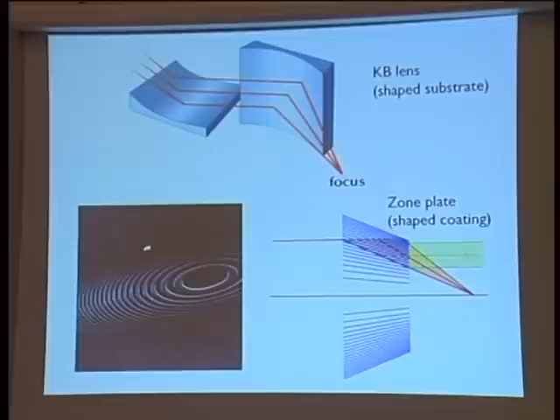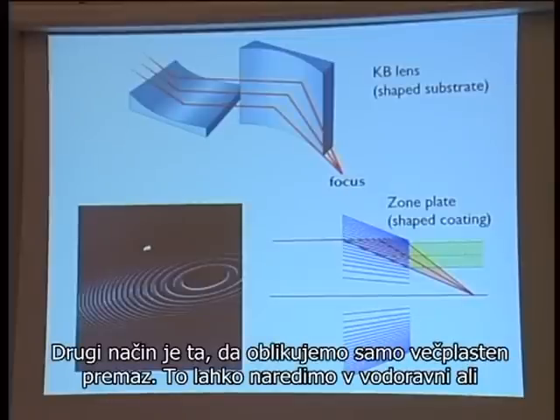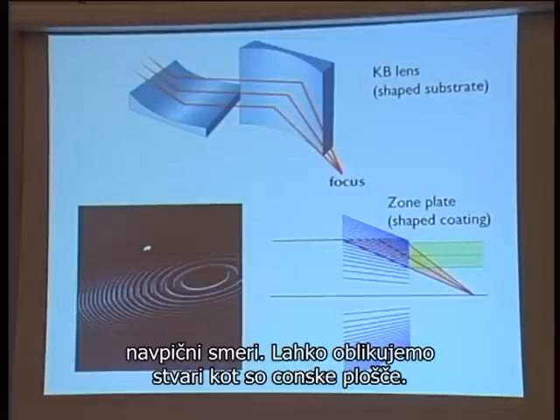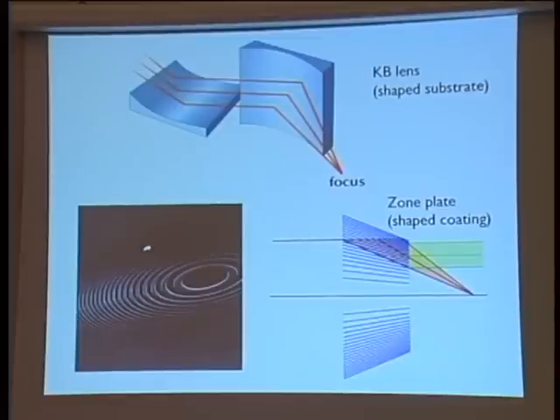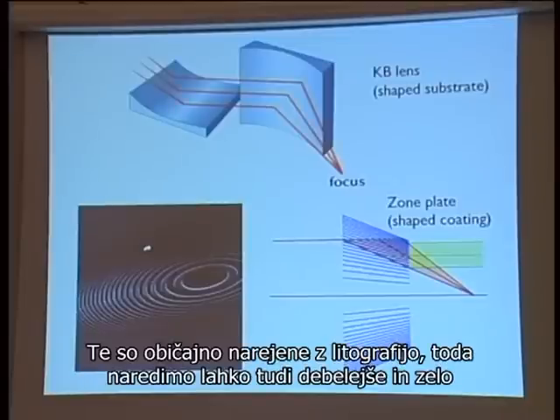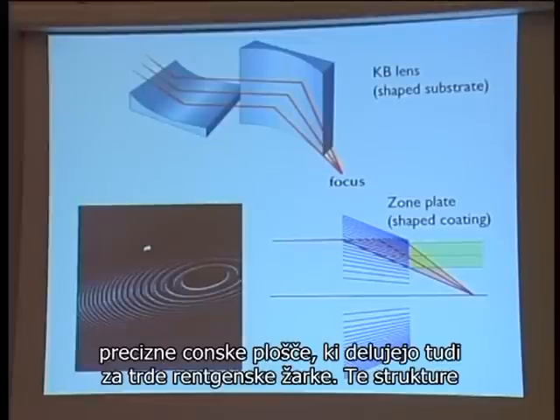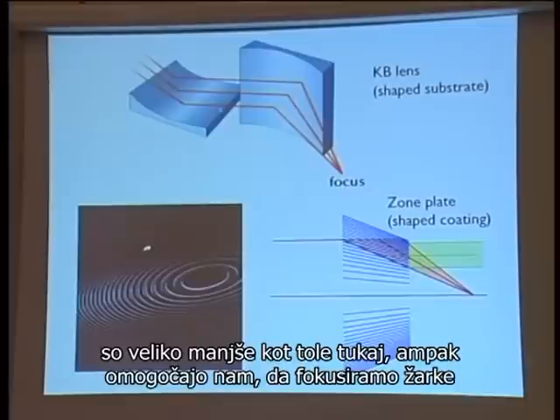And the other one is to shape the coating itself, the multilayer coating. We can do that in lateral and vertical direction, basically in both directions. And we can form things like volume zone plates. So zone plates are usually made with lithography, but we can make also thicker and very precise zone plates that work also for hard X-rays. So these structures are much smaller than this here, but they enable us also to focus X-rays to much smaller dimensions.